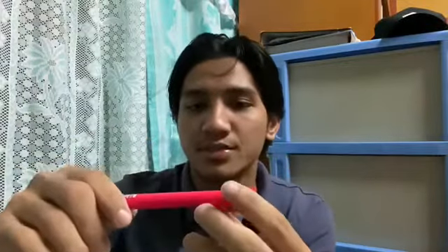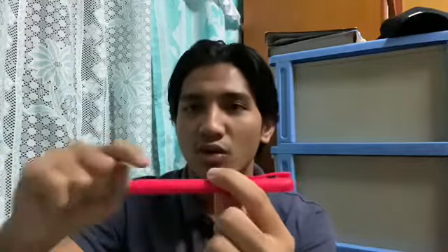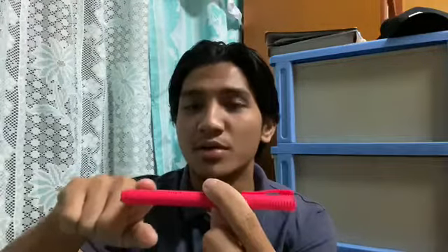We know that from the hardness test, the hardness decreases from the quench end of the rod towards the opposite end of the steel rod. So we can say that the hardenability of the metal also will decrease progressively from the quench end towards the opposite end of the steel bar. Alright, from the expected result that has been discussed earlier, we can conclude that the higher the cooling rate of the treated material, the higher the hardness and the hardenability of the material. So for this case of the steel bar that has been quenched at one end, both the hardenability and the hardness of the tested steel bar will decrease from the quench end of the bar towards the opposite end of the bar.